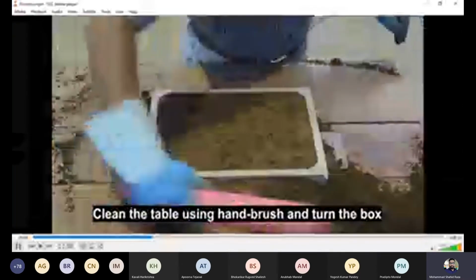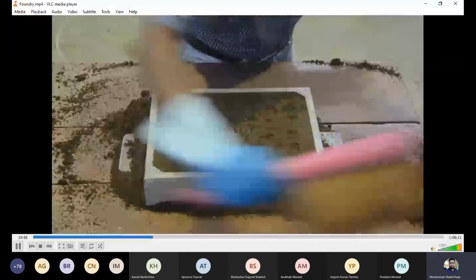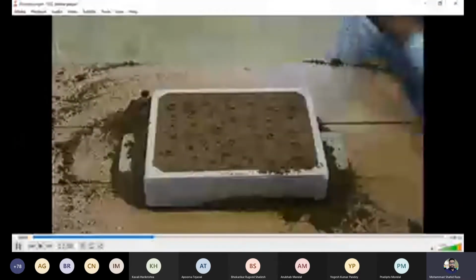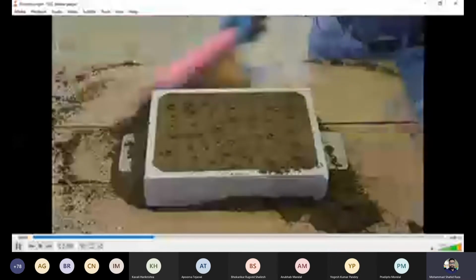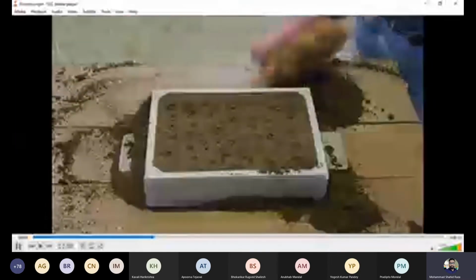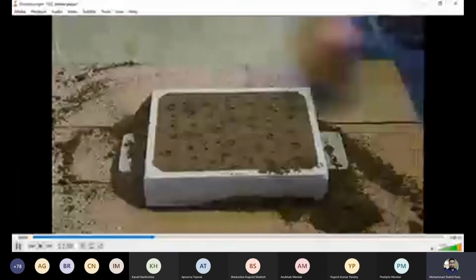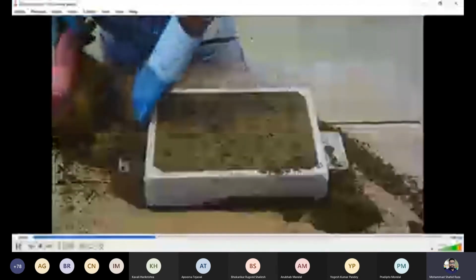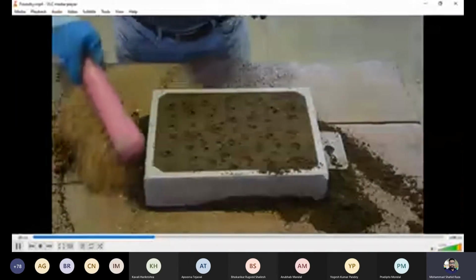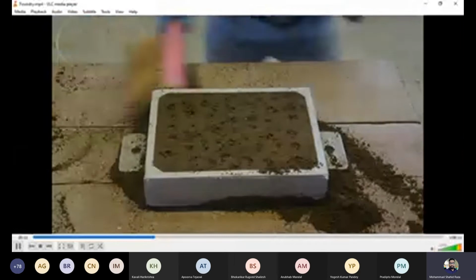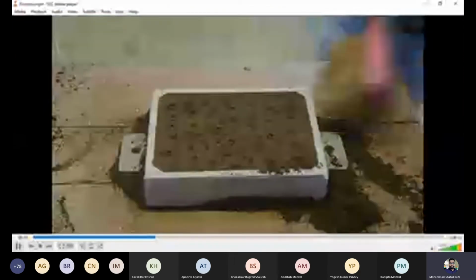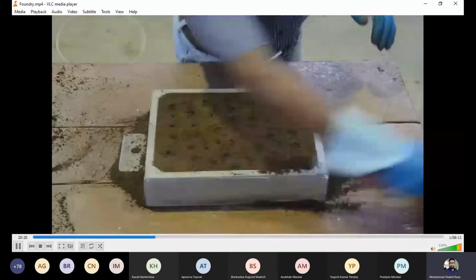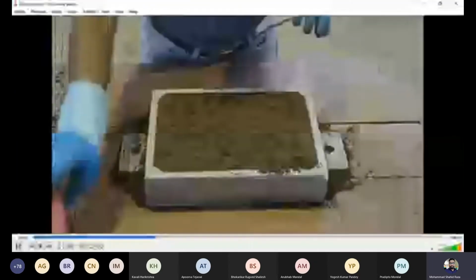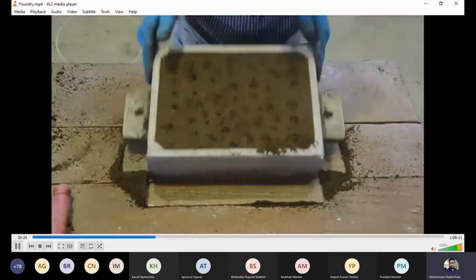The venting of the gases from the mold is facilitated by making holes which are not deep enough. They go only to puncture the backing sand layer, but don't puncture the facing sand. Had they punctured the facing sand layer also, it would have led to the leakage of molten metal through the fine holes. So these holes help in the escape of gases from the mold. We call this property of the mold permeability.